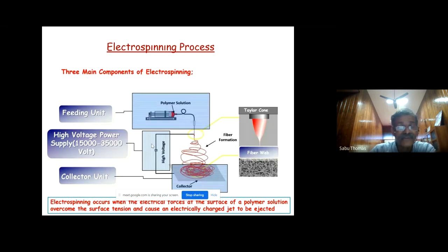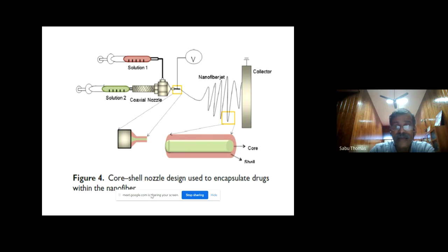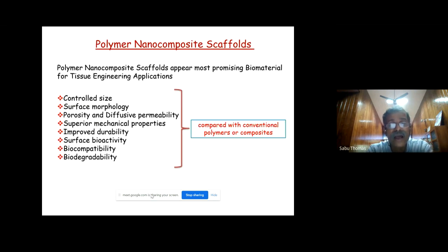If you look at electrospinning, it's a very simple process. You make a solution, and in the solution, you can introduce all the bioactive agents, nanoparticles, nutraceuticals, and then you can go for an electrospinning process. It's a horizontal way or vertical way you can electrospin the system. And you can have a shell and core. Different configurations could be possible in the electrospinning process. And polymer nanocomposite, when you put nanoparticles into polymers and do electrospinning, you can make beautiful polymer nanocomposite. You can also introduce nutraceuticals during the manufacturing process. And nanocomposites provide lots of beneficial effects: good mechanical strength, cell proliferation, cell attachments, faster degradation process.